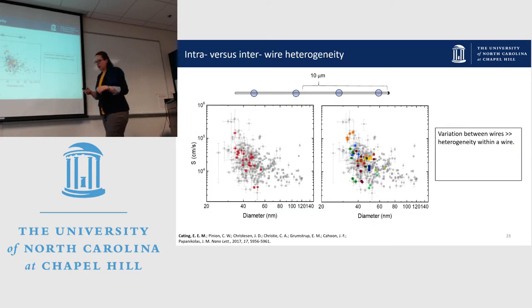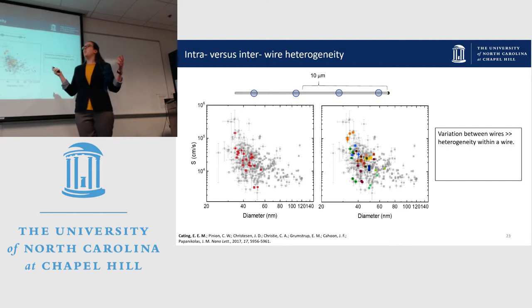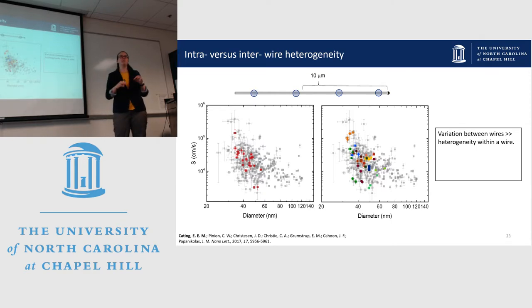So I looked at a few more. And we were working under the assumption that the region of the wire that's closest to the catalyst is probably going to have the best surface. It's the part that was grown last, and so it's going to be the most pristine. So the first thing I did was I found 23 nanowires where I could see the gold catalyst in the SEM, and I looked at the surface recombination within 10 microns of that catalyst. And that's what's plotted here in red. And you can see that while maybe the scatter is a little bit less than the scatter of the population as a whole, it's still similar, right? So this suggests that, okay, there is still a lot of variation that we see from one wire to another.